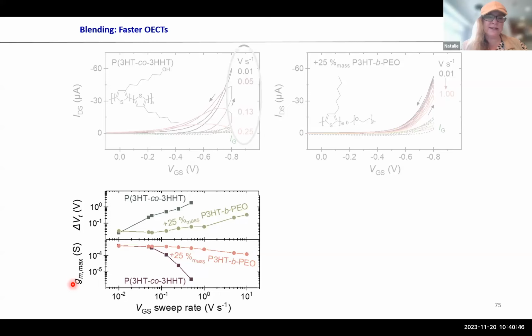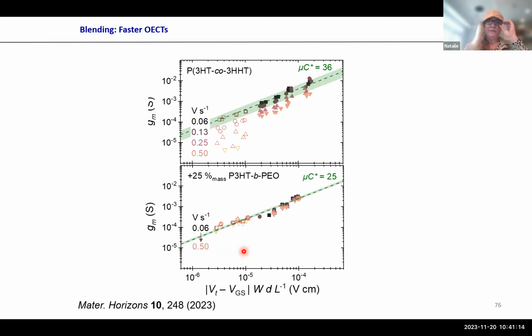The other characteristic that is important is the transconductance. It gives you really how easily you can change the current. And again, while at the beginning the neat material has a pretty decent transconductance, it goes to pot pretty fast once you scan fast, versus in the blend, it's actually pretty okay.